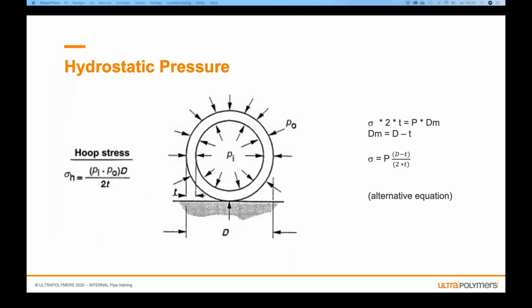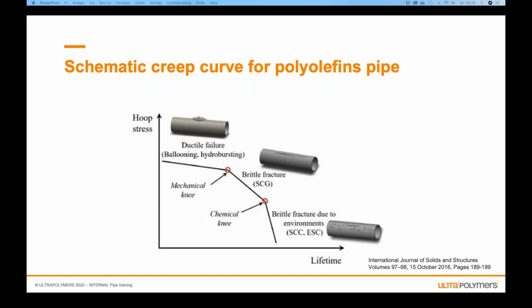Since pipe is a very easy design, it's round, hoop stress is the most common test in pipe. So you have a pressure inside the pipe and you have a pressure outside the pipe. The pressure inside the pipe is, for instance, gas or water, and outside you have the soil, and if it's in a street, you have the trucks driving over it, and so on. And then you have a calculation that you can see on the left side, or at the right side. That's an alternative equation. And when you know the pressure inside, you know the pressure outside, and you know the diameter of the pipe and the thickness of the pipe, then you can calculate the lifetime of the pipe. And schematically, you get a creep curve for the pipe.